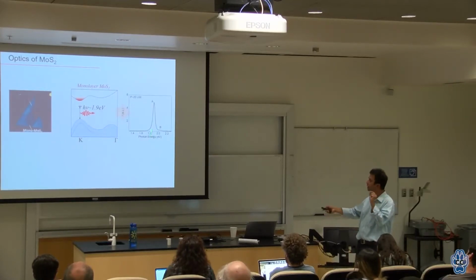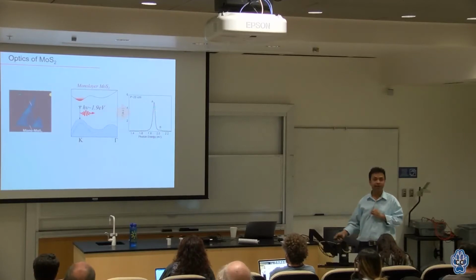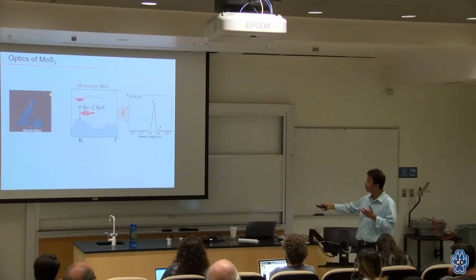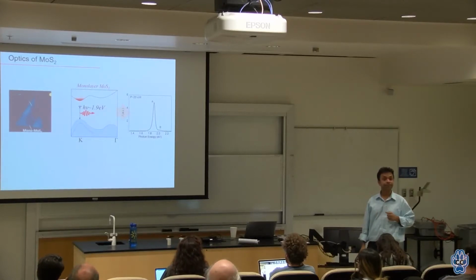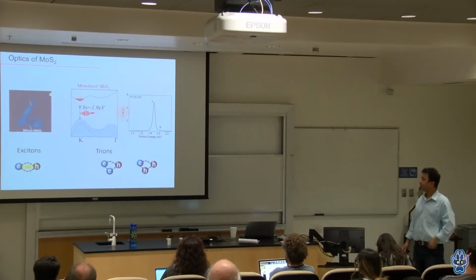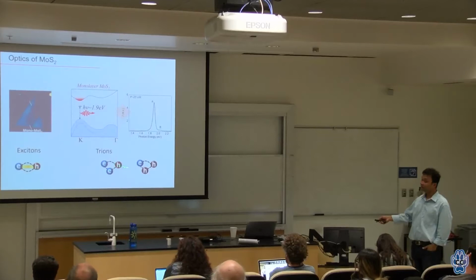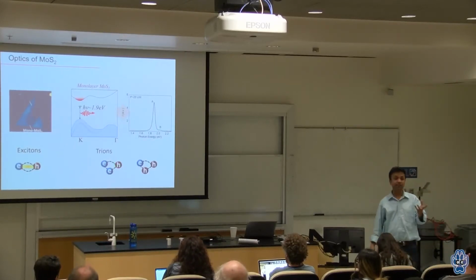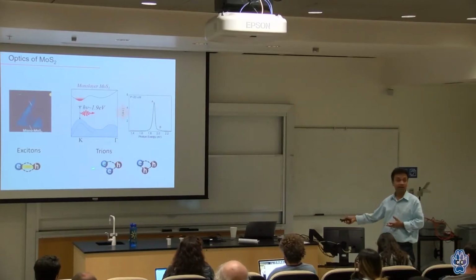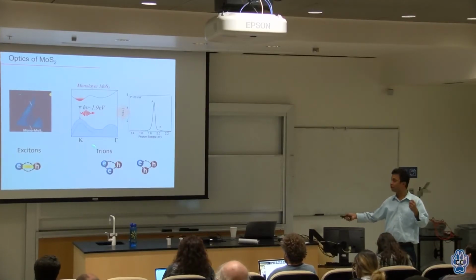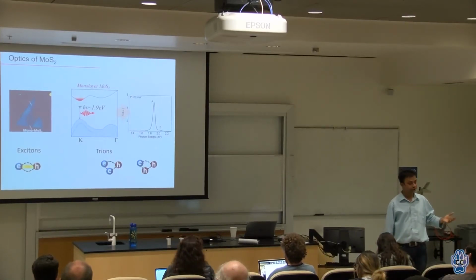That means I'm hitting this sample with green light and measuring the light coming out. You can see this is a room temperature measurement. I can see the A peak, when the transition happens from here, and I can also see the B peak, when the transition happens from the bottom one. Not only that, because it's a very strong interaction, I can also create a three-body system called a trion, which can have two electrons and one hole, or one electron and two holes.